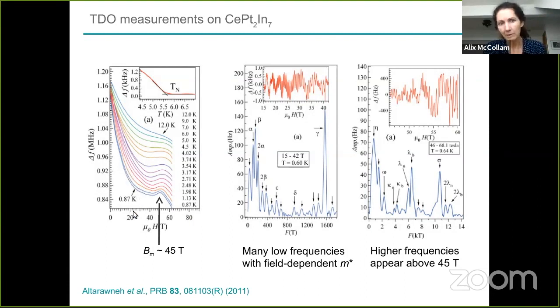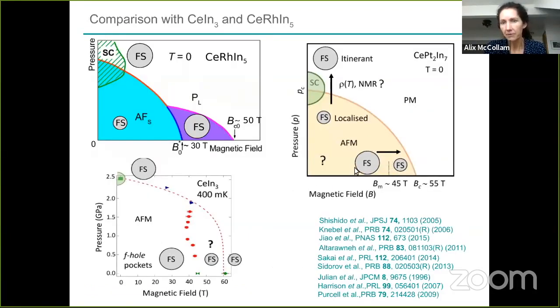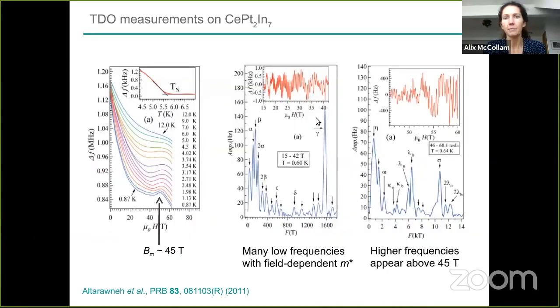So this looks a little bit like resistivity as a function of field. They saw a strong feature here around about 45 Tesla, which is what gave rise to this discussion about something happening at 45 Tesla in the phase diagram. Below 45 Tesla, they see a certain set of quantum oscillations, many low frequencies, and a field-dependent quasi-particle mass. And then above 45 Tesla, they see some higher frequencies emerge. So this gamma and these higher frequencies start to show up in their data above 45 Tesla.